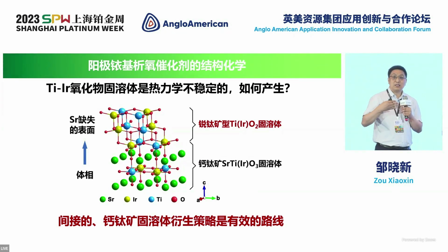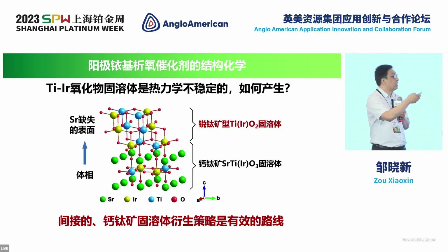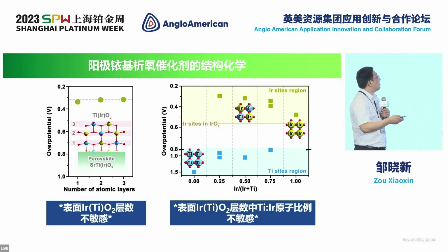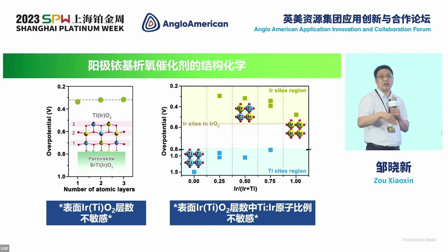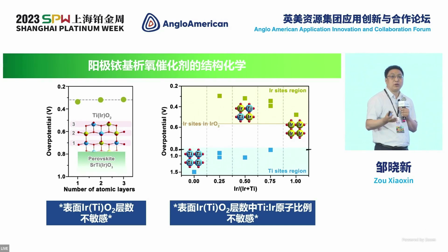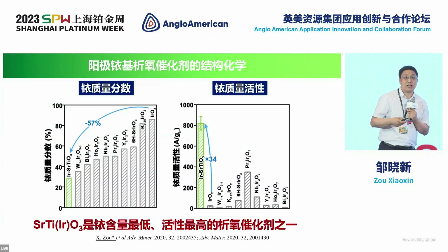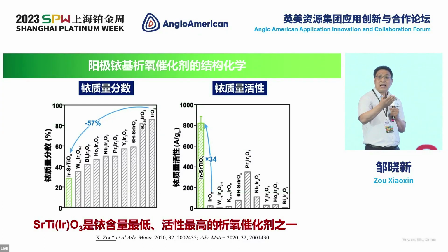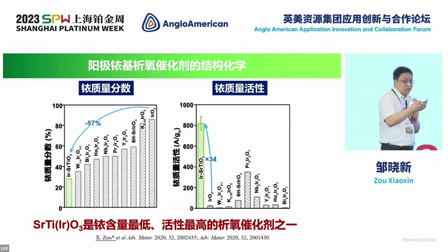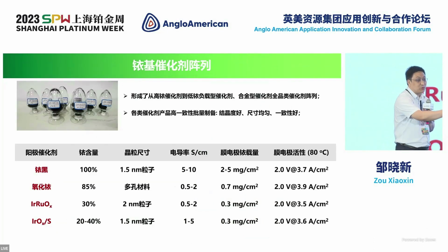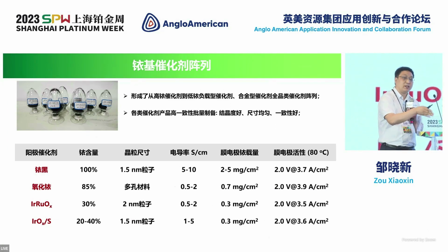So how do we achieve our final goal? Well, what we do is combine the strontium titanium trioxide solid solution with the titanium iridium dioxide solid solution. We also find, by calculating these different layers of titanium dioxide and the proportion of the atom numbers of titanium and iridium, that we can produce such a catalyst. Through this chart, you can see that with a reduction of 57% of iridium atoms, we can actually improve the activity by 34 times. So this is one way we can achieve that.